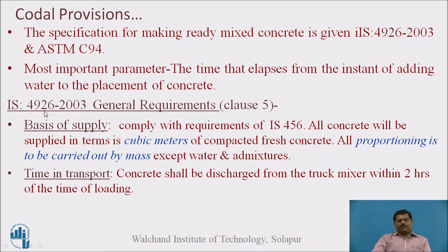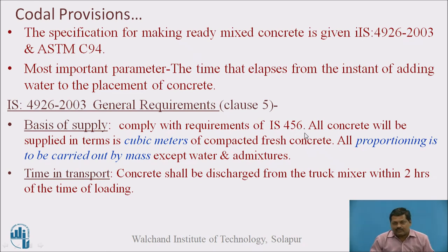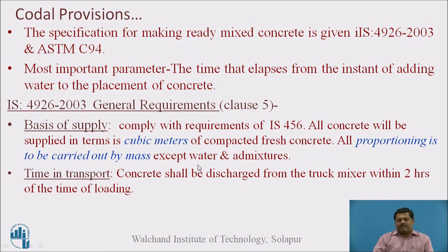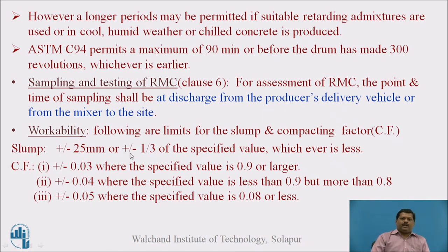Let's see IS 4926-2003. General requirements: Clause 5 starts with the basis of supply — it must comply with IS 456. All concrete will be supplied in terms of cubic meters and all proportioning is to be carried out by mass, except water and admixtures. Ingredients must be proportioned by mass and concrete supplied by volume in cubic meters. Regarding time in transport, concrete shall be discharged from the truck mixer within two hours of loading. For longer periods, it may be permitted if suitable retarding admixtures are used in cool or humid weather, or if chilled concrete is produced.